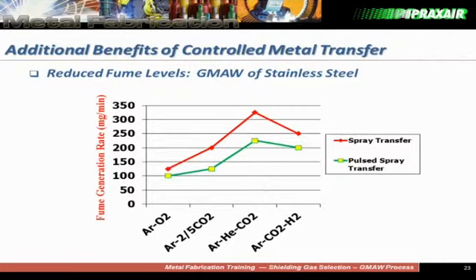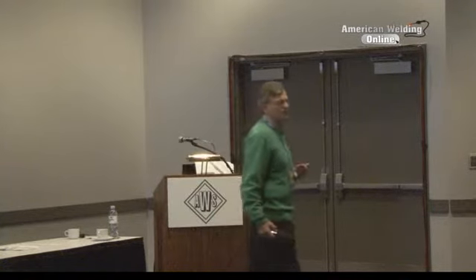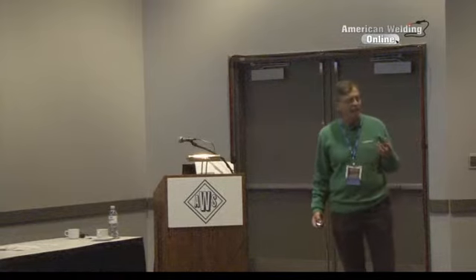We mentioned earlier that shielding gas selection can affect the fume generation. This is just a comparison of conventional spray arc welding with stainless steels versus pulsed arc welding with some different shielding gas blends. And as you can see, pulsed welding reduces the fume level even from conventional spray welding, which is already pretty low, but it can reduce the fume by 25 to 50%. So again, process selection.